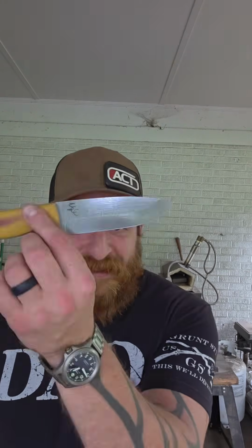So these knives that I heat treated, these right here, were done with that heat treat protocol. These were all 1650 or 1700 and a 425 or 450 degree temper. I got to find the numbers exactly. These all came out at 62 Rockwell. And they should have north of 40 pounds of toughness, which is crazy.